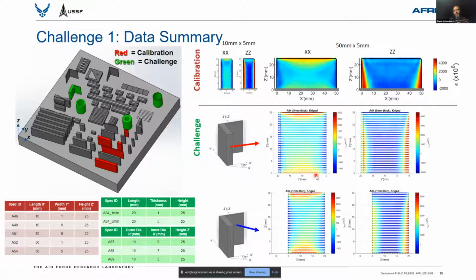The highlighted components were part of this challenge. The red items were basically flat walls of varying length and thickness that were provided as part of the calibration data set. So the residual strains I'm showing in the top row of images here were measured, and those were part of the problem definition. And we asked folks to predict the strains that would evolve in these green components, a series of tubes effectively, as well as an L-shaped structure with walls of varying thickness.